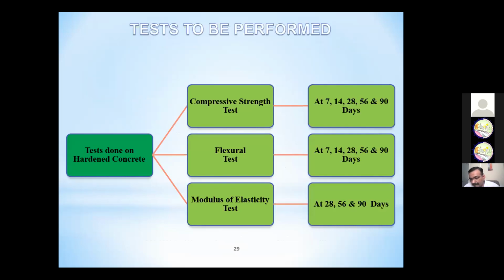Now, the tests to be performed on hardened concrete: compressive strength, flexural strength, and modulus of elasticity. I did almost 17 tests on this work, but as per the IRC, only the design-point-of-view tests are required: compressive strength, flexural strength, and modulus of elasticity. So in this work I put compressive strength at different ages: 7, 14, 28, 56 and 90 days, but I went up to 360 days, one year, from the durability point of view. Then flexural strength at 7, 14, 28, 56 and 90 days, and modulus of elasticity at 28, 56 and 90 days.